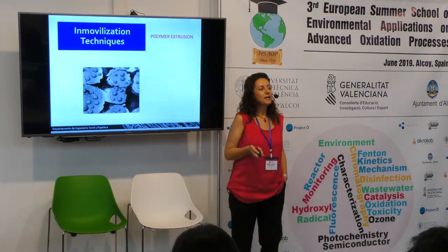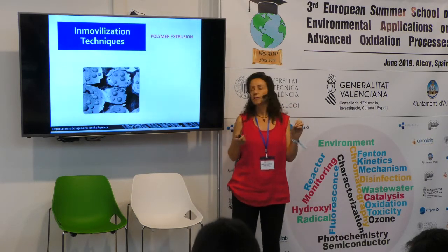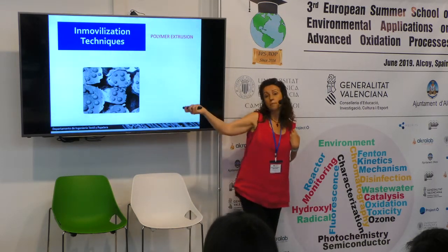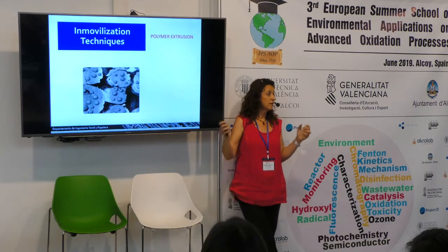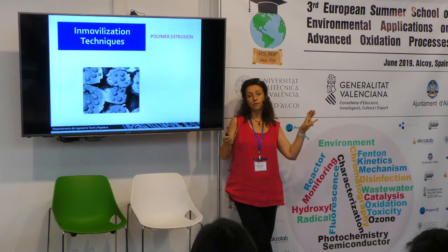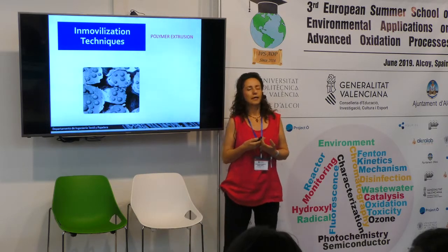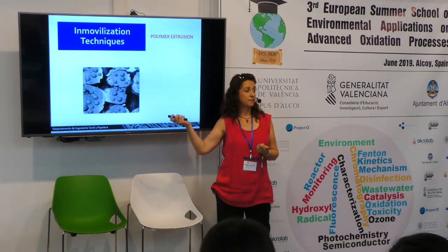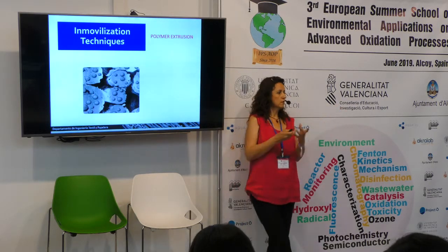Now, okay, when we have the polymer melt and we spin it through the spinning process, we can obtain the fibers. If I include, for example, the microcapsules or the nanoparticles in the melting polymer, then they would be entrapped in the fiber. So I would have these products in the fiber. Which is the problem? If I'm going to include, for example, silver nanoparticles, obviously, when I've got them inside the fiber, the antibacterial effect would last as long as the fiber would be in its shape.